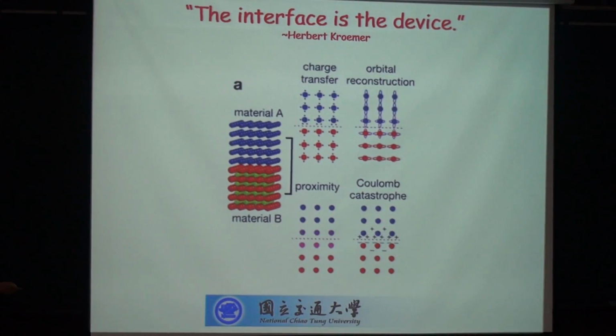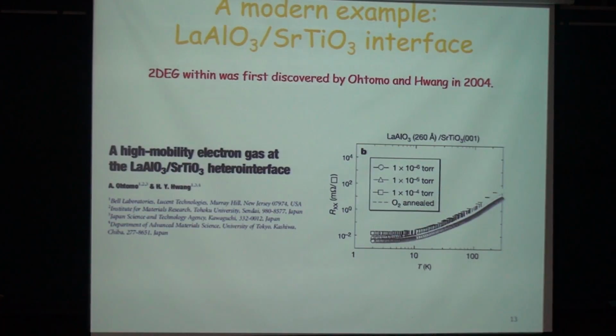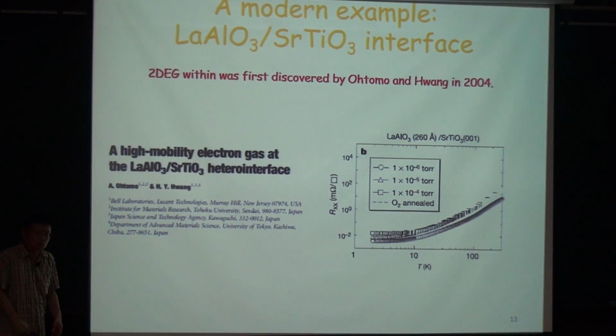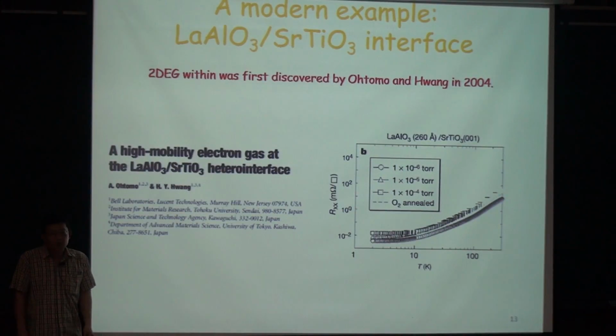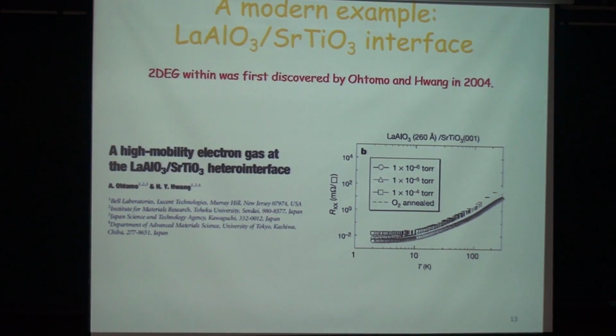To go to an even more solid example, let me first introduce a modern example of this heterostructure and the interface. This is the LAO and STO interface. What's special about this interface? Well, it's really quite bizarre. For example, this is an insulator. This is another insulator. They are very much insulating. If you really do the measurement, you would get a very large resistance at room temperature, and when you go to low temperature, you even cannot measure it because the resistance is simply too large.